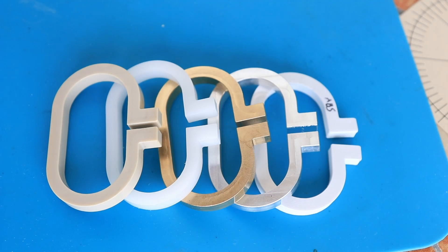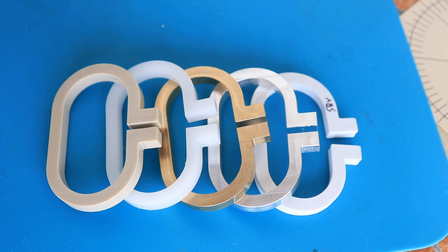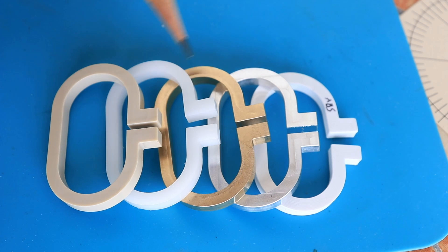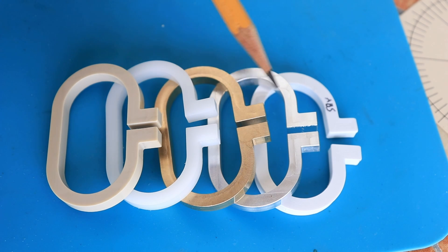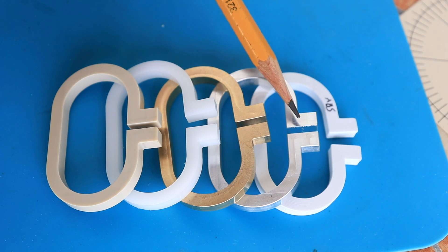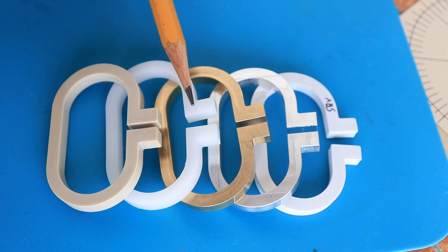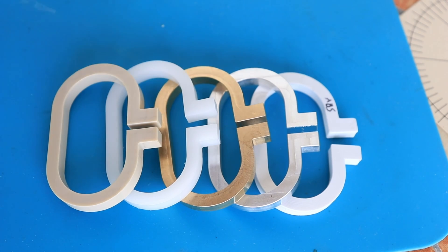And now removing of the load. And this is how they look like after approximately 10 minutes after I removed the load. Basically the PEEK is interesting. And the brass got its original shape. Just a little bit more permanent deformation on aluminum. And the ABS and the POM are very similar now.